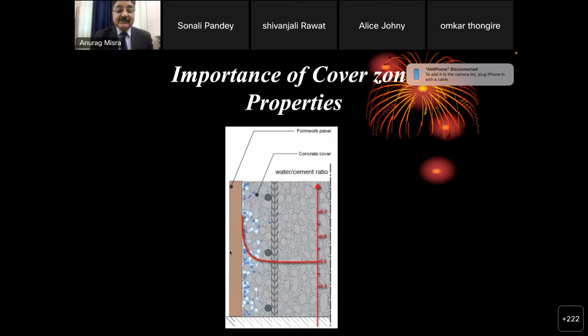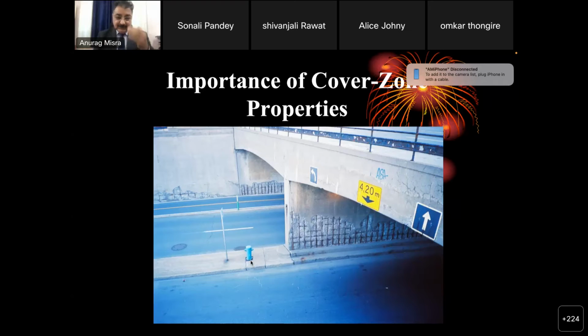So that results in, because this area becomes quite porous, a bad quality structure where early deterioration is expected. So we need to actually look for these things and try controlling that. You can see that here this cover concrete is going because of corrosion of reinforcement, ultimately reducing the diameter of the reinforcement and reducing the load carrying capacities of these structures.